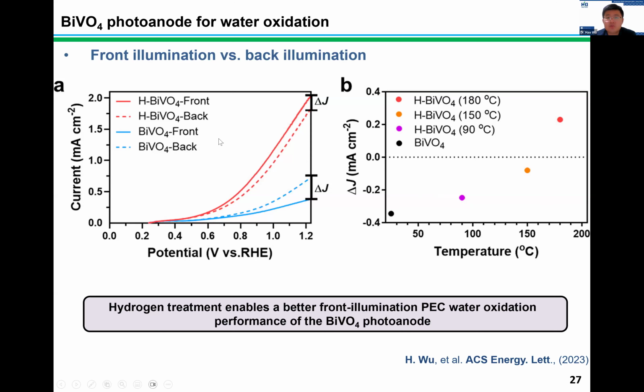Because mostly due to the polaron interaction, the electron transport in bismuth vanadate is poor, so the back illumination generally shows a better performance compared to the front. But with the hydrogen treatment we remediate the polaron behavior, and we achieve a better front illumination performance. And this finding is particularly meaningful to tandem research. Maybe you know that when we do the photoelectrochemical water splitting, we can make a tandem cell.